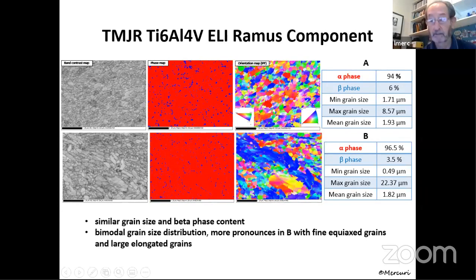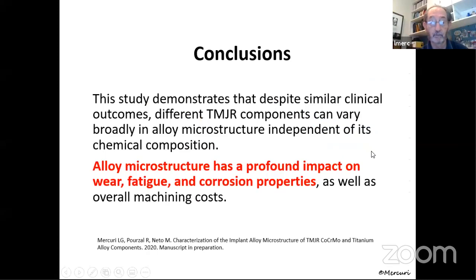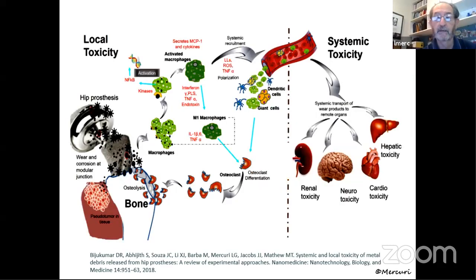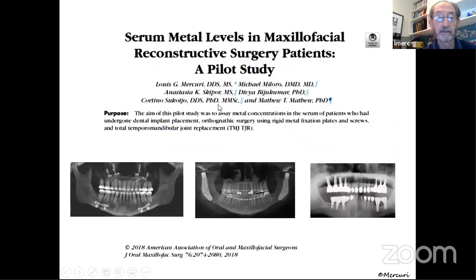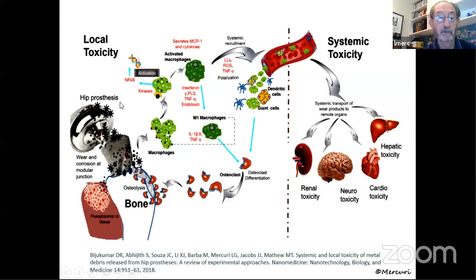So let's advance. The conclusion from this study was that the alloy microstructure has a profound impact on the wear, fatigue, and corrosion properties of any device. Now, as I said earlier, we not only have particulation of the material itself, so particles of polyethylene and particles of metal can actually come off, but we also have ions that come off. And the ions are the most concerning. And I don't have a lot of time to talk about that, but we know from our